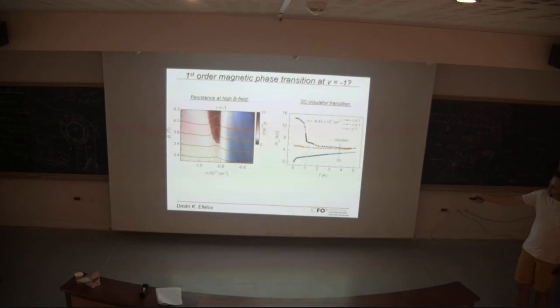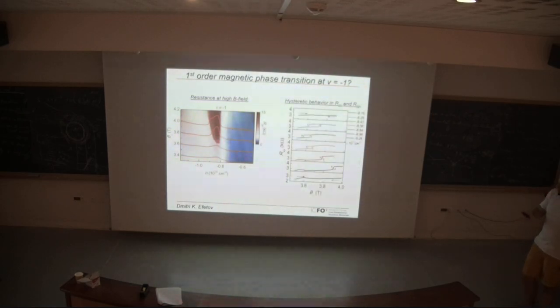So in some locations, for example for nu equals -1, if we increase the magnetic field, we enter a region where we observe a sharp resistance jump, and if we plot along this line as a function of temperature, we observe a superconductor to insulator transition. And interestingly, along this line in magnetic field, if we sweep the magnetic field up and down, we also observe signatures of hysteresis, which is very narrowly located around the integer number. If we go slightly to the hole or the electron side in doping beyond this state, hysteresis vanishes, and hysteresis is really strongest directly at integer -1 filling here.